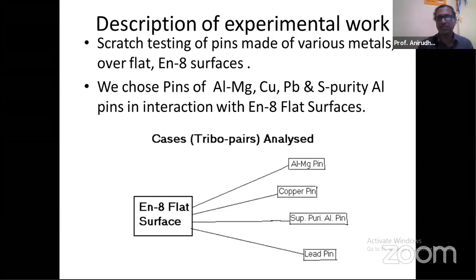When we did scratch tests on steel surfaces made of EN8 flats, we used 4 different materials, which are shown there in this new slide. We made pins of aluminum magnesium pin, copper pin, super purity aluminum pin, and lead pin. So that means we used 4 different combinations of materials. Then we changed the surface features of this hard substrate, or the bottom material of the surface, which is the EN8 flat surface.